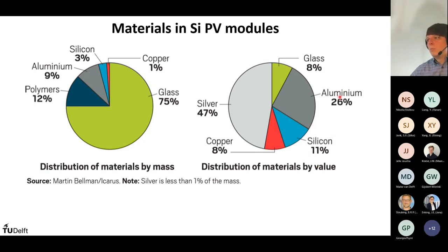So these are the materials that we would like to get back in recycling. However, what happens now, we have a law that states we need about 80% of materials recycled. So we take the glass, we crush it, and we use it as low-level filler material, not even window glass, which would also already be a downside. We use it as filler material in roads and maybe glass wool if we have a higher level process. So that's really a pity.